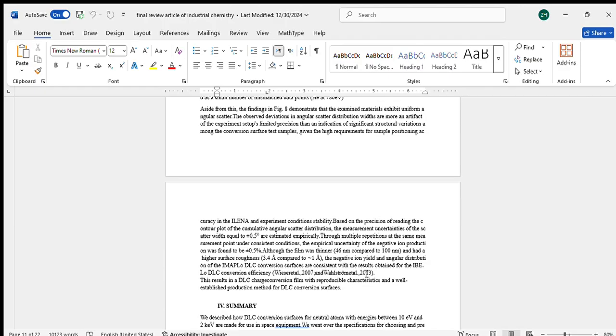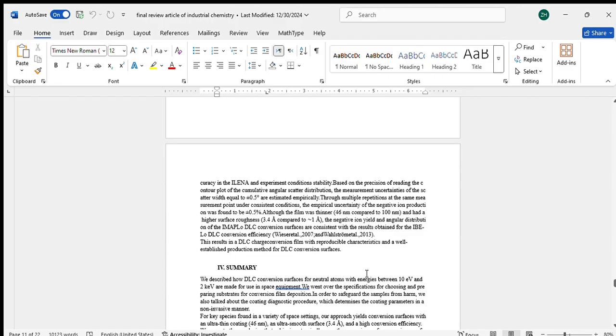So to improve this, the thickness of the DLC film was reduced to around 40 nanometers, resulting in a much smoother surface and better conversion efficiency, similar to the results seen with the IBE-Lo DLC conversion surfaces.